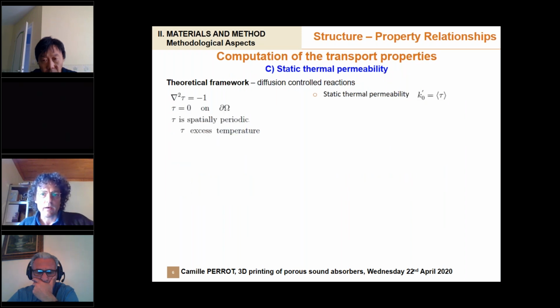Finally, we can also deal with a third fundamental problem, boundary value problems, which is basically related to the dissipation of heat in the low frequency asymptotic regime. And from this boundary value problem, you can extract a last macroscopic parameter, which is the thermal static permeability, which is basically the average of the excess temperature when solving this boundary value problem.